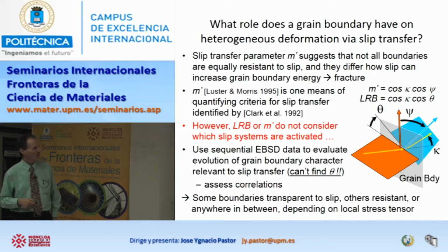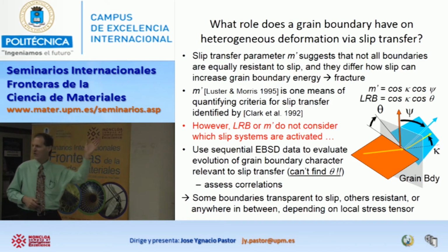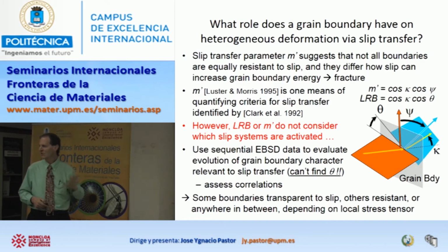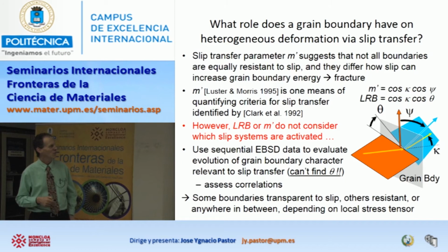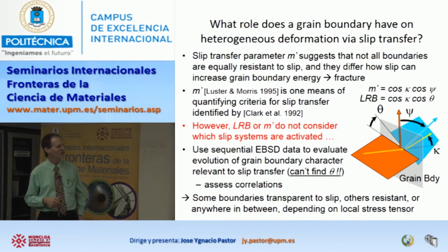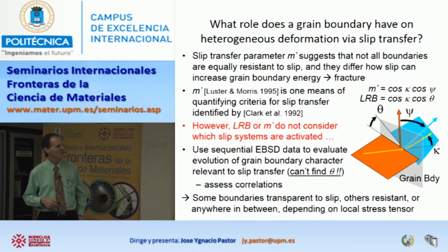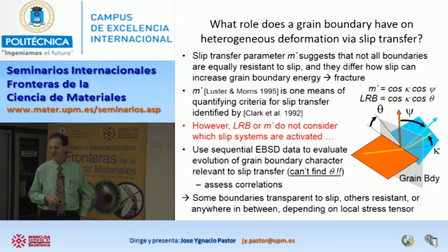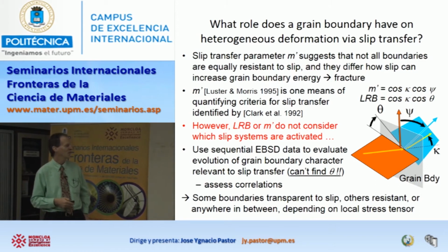It turns out that if I use EBSD, electron backscatter diffraction data, to evaluate the evolution of grains, I cannot find theta, which is this angle in the grain boundary plane, because I don't know how the grain boundary is tilted with respect to the surface. So we're going to use this M prime right here, which just has to do with the grain plane normals, because that's something we can figure out based upon just a surface measurement.